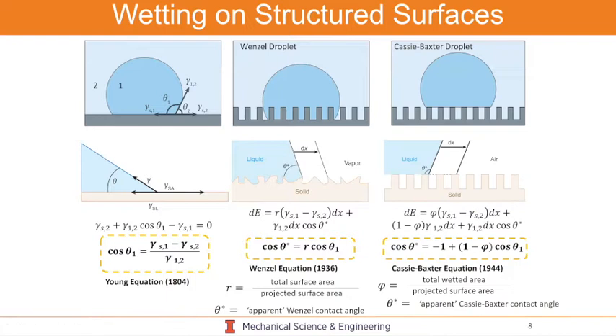But it turns out when you add roughness, you could actually have extremes in wetting states. So if you have roughness of a certain length scale and a certain contact angle on the intrinsic surface, you could undergo formation of these Wenzel droplets dictated by the Wenzel equation, or what we typically see and what I've been showing you so far in the past videos, what we call Cassie-Baxter droplets. And these are actually two independent scientists, one named Cassie, one named Baxter. They developed this in 1944, where they showed that if you have a highly non-wetting surface and then you structure it, you're actually forming more and more air pockets beneath the droplet. And because of that, this droplet is becoming more like a suspended spherical droplet in free space. And hence, it'll take very, very high contact angles. These contact angles here can actually approach 180 degrees.